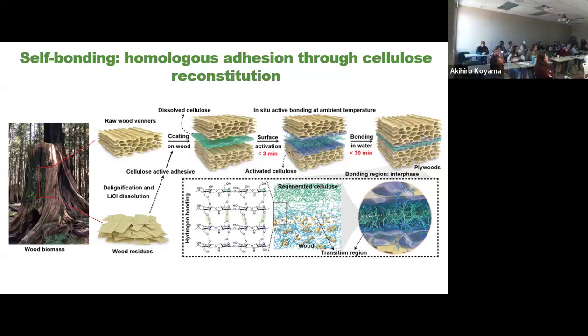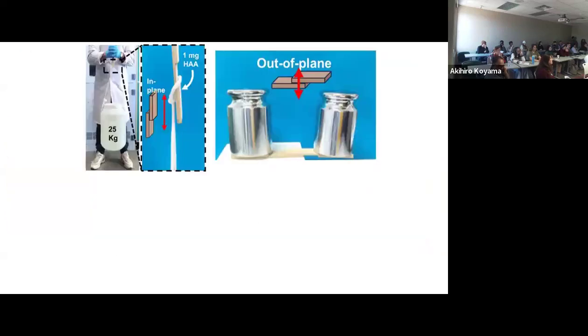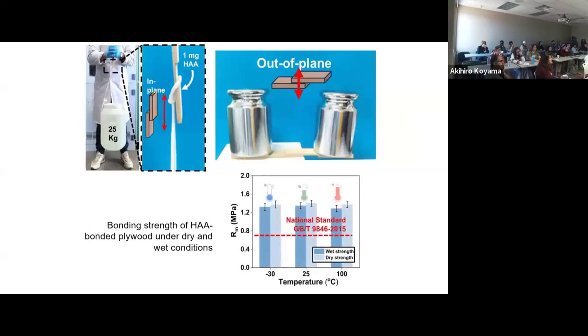And of course, we have been looking into how this happens at the molecular level. So we're looking into molecular dynamics simulation, coarse-grain simulation, to see how the cellulose that is in the hydrated state, when water is removed, achieves this very strong binding between the surfaces, right? So it all goes down to cellulose. And the fact that cellulose is a homopolymer, a linear polymer, highly hydrated, when you remove water, then you will have a strong bonding between the materials, including hydrogen bonding, van der Waals forces, and many other interactions. It works very well. And the materials that you achieve are found to have very high shear strength or bond strength, quite remarkable values, both in plane and out of plane.